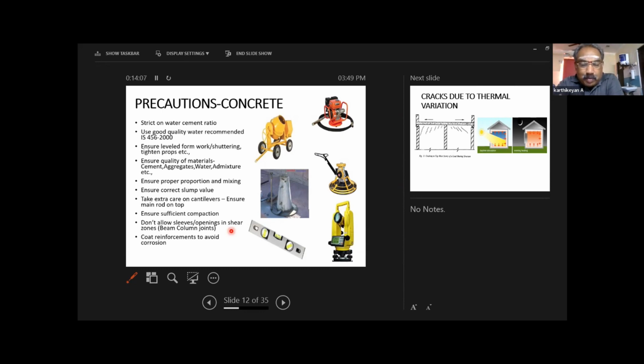The formwork should be straight enough, and the shuttering and props you should double check, because once you load it, if there is a small bend, tilt or settlement, that will make an uneven shape and then there are chances of sinkage cracks. And ensure good quality materials. Purchase good cement.